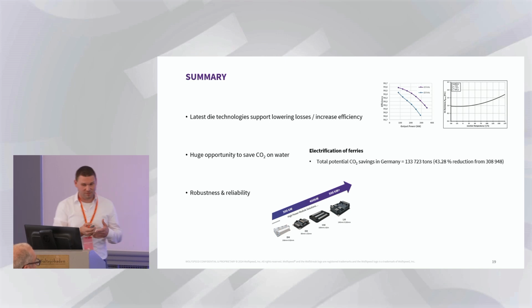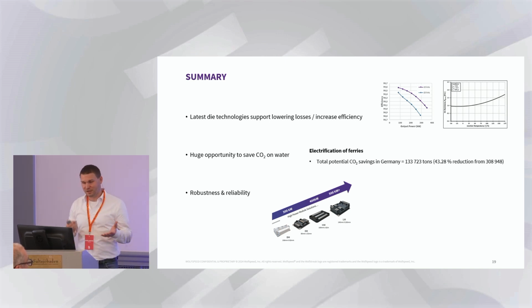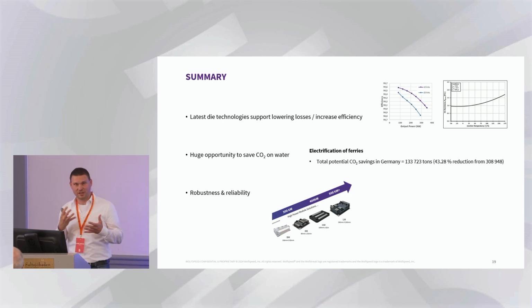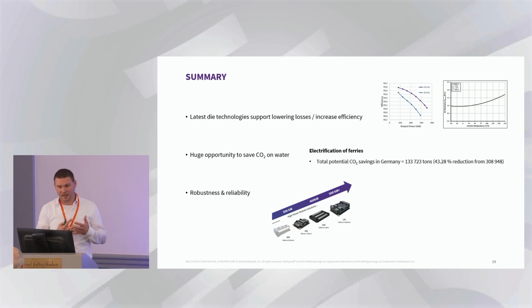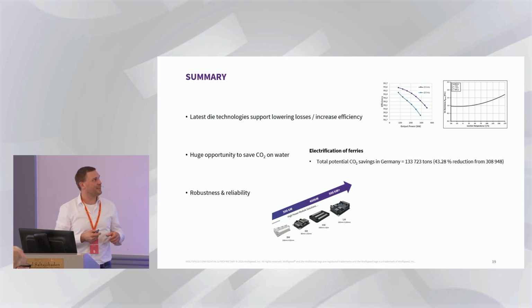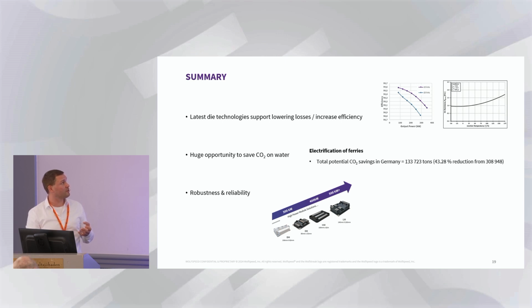Concluding my talk, using the latest die technologies, we try to lower the losses, we try to switch as fast as possible. It's high dV/dt, high dI/dt. We would like to increase the efficiency, and it helps that you have a quite stable RDS(on) over temperature. It's not increasing too much, and especially the soft body diode for the new generations is going to help a lot in faster switching, especially in DC-DC applications.